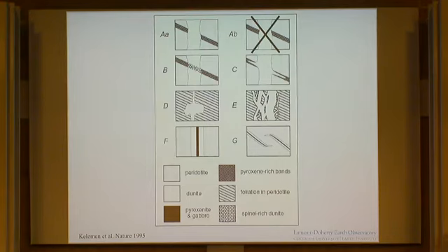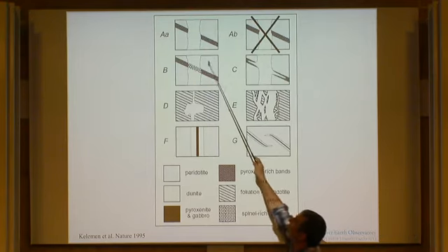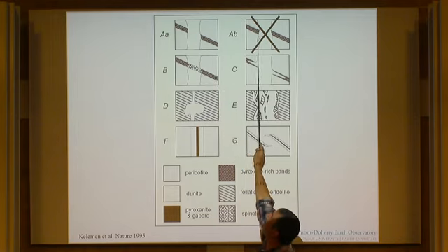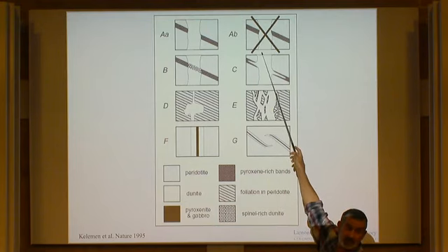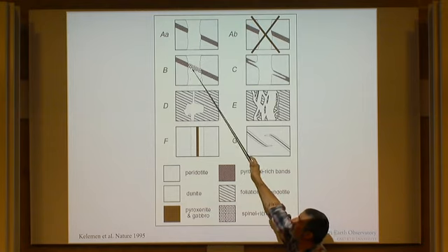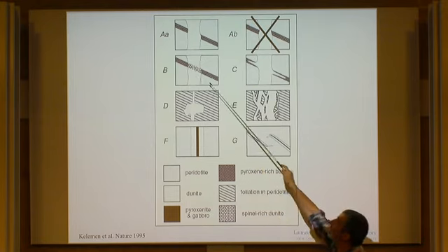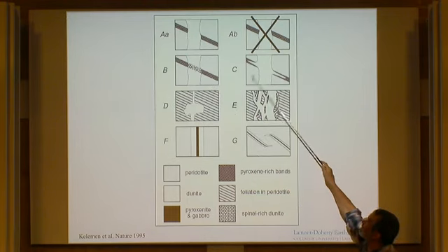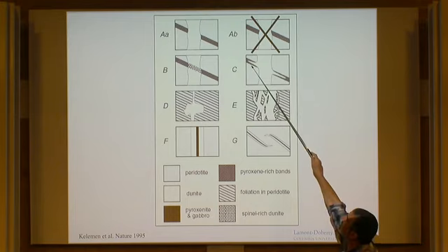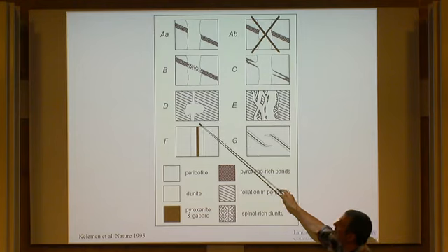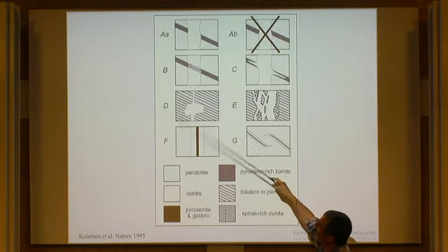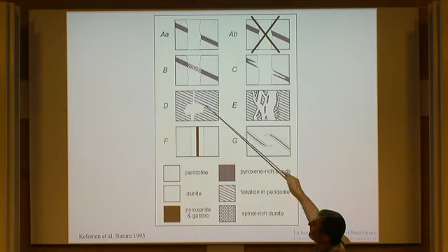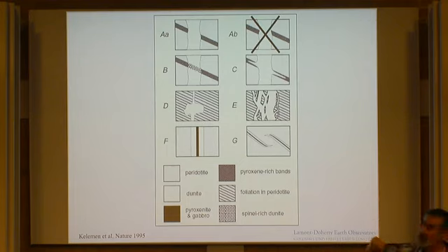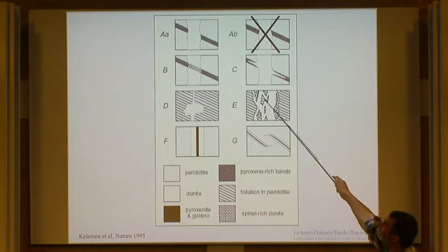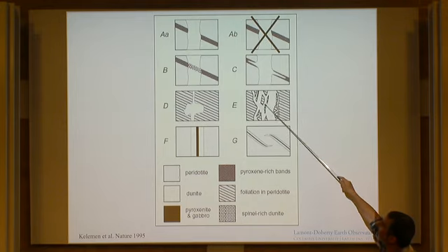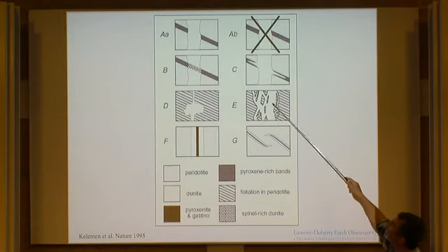And so here's a little summary diagram. So we see no displacement of planar features across dunites. If they were dilational and filled with minerals, they would look like that. We see these relic spinels sometimes, which really shows, without a doubt, that the dunite is replacing the rock that it's in. We see preferential replacement of pyroxene-rich bands. We see big circular features in the dunites that are not accompanied by deformation in the surrounding rocks. We see this anastomosing texture that I already referred to, where the pieces don't fit together anymore unless the dunite used to be the wall rock, and also they're not rotated.